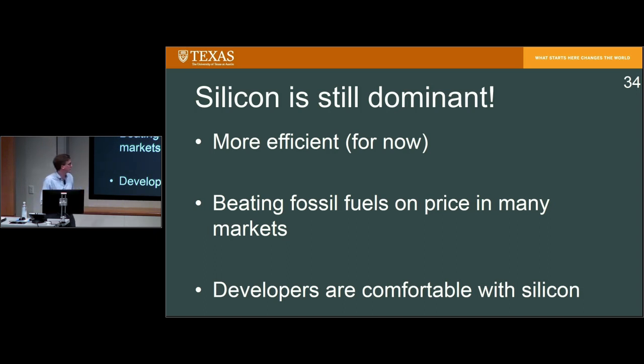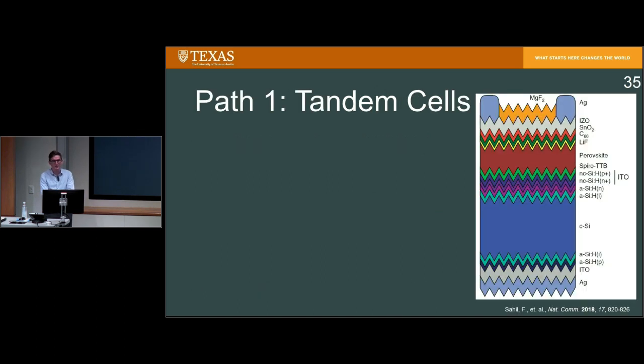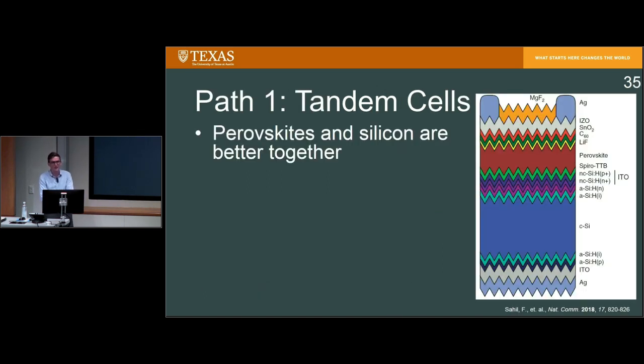And additionally, developers are very comfortable with silicon. So how are you going to convince them to change their comfort zone to a new material? And I think there's a couple different paths you can take. I think the first one is kind of like a cowardly path, is to say, no, we're not going to compete with silicon. Perovskites and silicon are better together. This is a tandem solar cell type of architecture. The idea being, in an individual solar cell, you can only get up to 34% efficiency. And this is because you have a trade-off between the amount of solar spectrum you can absorb and the energy that you can extract from each individual electron you generate.